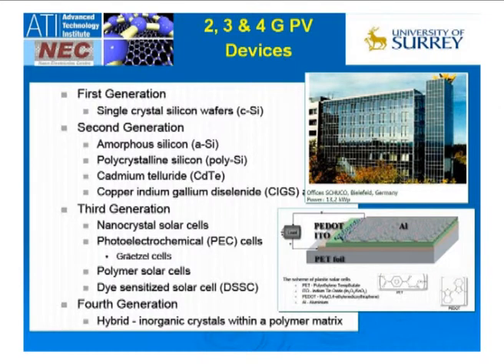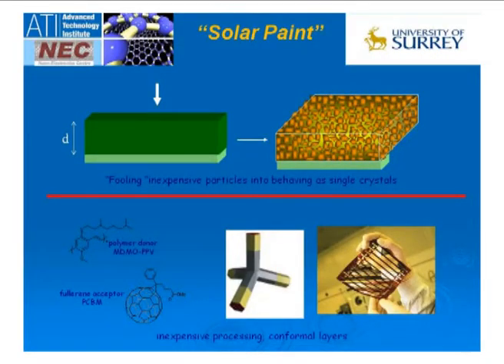So, as indicated, you have the 1st generation single crystal, 2nd generation amorphous silicon, polycrystalline silicon based materials. The 3rd one had the dye-sensitized solar cell, the polymer solar cells. But the 4th generation one is looking at the hybrid materials. And what is a hybrid material? A hybrid material really is looking at making the solar cell that generally has to be a few hundred microns thick much, much thinner. What it's trying to do is to create nanoparticles, nanostructures within your material that fools the light into thinking, oh yes, I've got enough area here in order to absorb the photons that are hitting that.